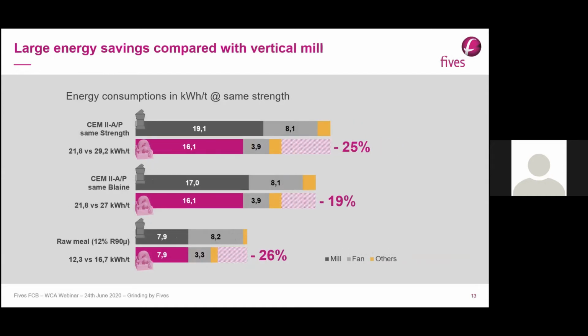But we also have significant saving compared with vertical mill. For sure, they are lower, but you can see on this picture 2 comparisons for raw mill grinding and cement grinding, and the range of saving is between 20 to 25%. I will comment a little bit later, but there are on this slide for the same cement 2 targets, either in terms of strength target or blaine target, because one of the advantages of the raw mill, we will see a little bit later, is that the cement quality can be reached at lower blaine compared to ball mill or even vertical mill. I mean, the same strength development is reached at lower blaine with the raw mill.